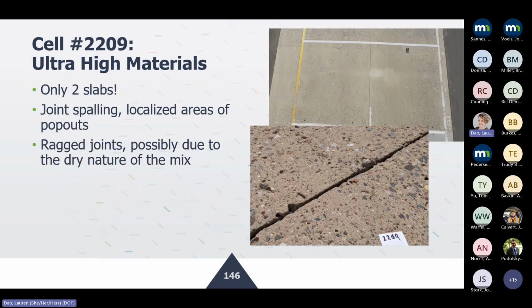And ultra high materials, like I said, only 15 foot left. You might miss it. You have to carefully observe this test cell while you're out there on your field visit today. Only 2 slabs. And again, it is there. No repairs have been performed since construction. The 2 slabs remain to this day, I believe. Ragged joints, possibly due to the dry nature of the mix, and some areas of localized pop-outs and joint spalling.